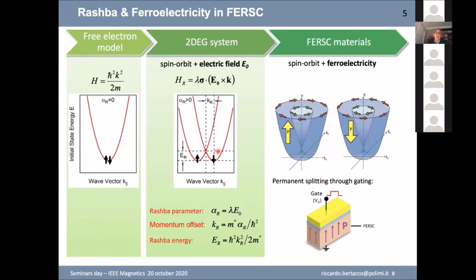So the interesting point is that here you have the so-called spin-momentum locking, which means that the spin will always be perpendicular to the wave vector of the electrons. And this is seen here in this three-dimensional sketch of the bands, in which you see that there is an outer band in which the spin circulates clockwise and an inner band in which it circulates counterclockwise. But in general, you cannot change it in a two-dimensional electron gas if you don't change the direction of the electric field, which is something volatile.